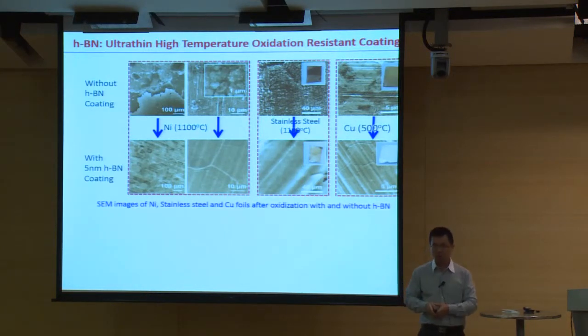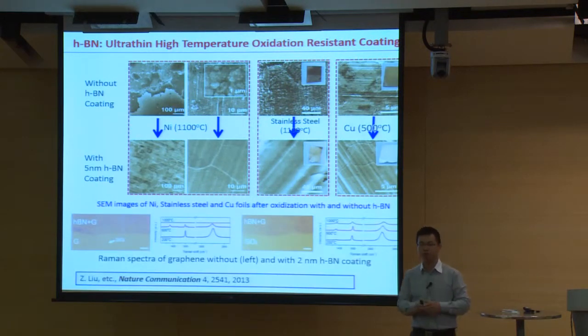And the same case for the stainless steel and the copper foils. And next, what will happen if we transfer this material to graphene? So here, we have a boron nitride part of the graphene. This part is graphene without boron nitride. This part is the boron nitride coated graphene. And then we burn it at different temperatures, from 200 degrees, 600 degrees, and 1,000 degrees. So from what you can see here, without coating boron nitride, graphene has been burned out, for sure, and there's no Raman signal from here. But with the coating of boron nitride, we can still find the signal from graphene. So this work means we can use ultra-thin boron nitride as a very good coating for both metallic surfaces and also for graphene, for high temperature workable devices.